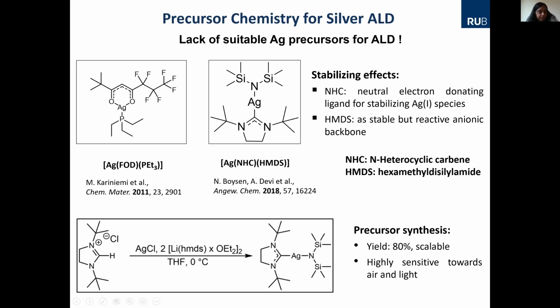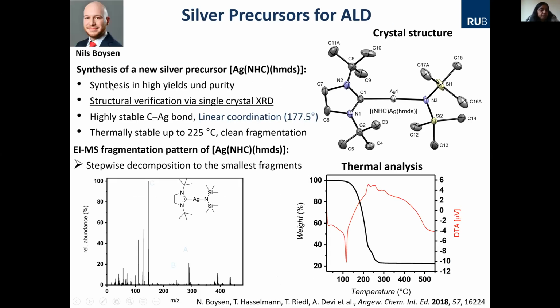Okay, so we synthesized it. It was a complex procedure in the beginning, but later on we optimized it. At the end, we got a very nice molecule. So you have a linear molecule, silver, with the HMDS, the hexamethyldisilazide, and the NHC here. And this compound was isolated. And what we did was also try to see how different it is from this precursor, or at least what the characteristics are. So Nils, the doctoral student, investigated this project, and then he found a linear molecule.